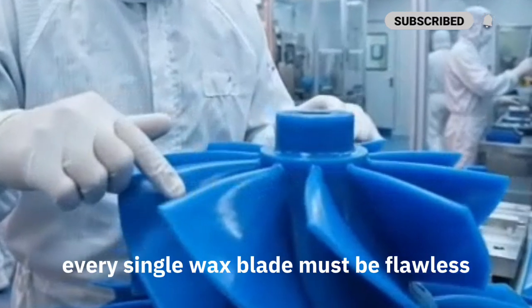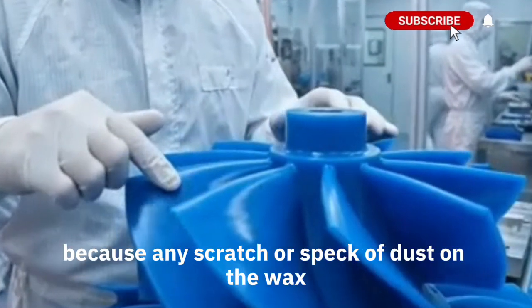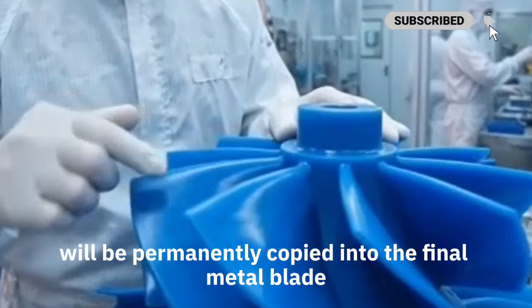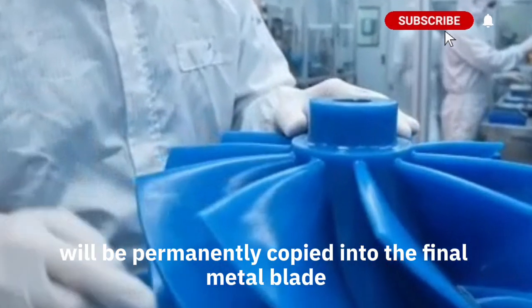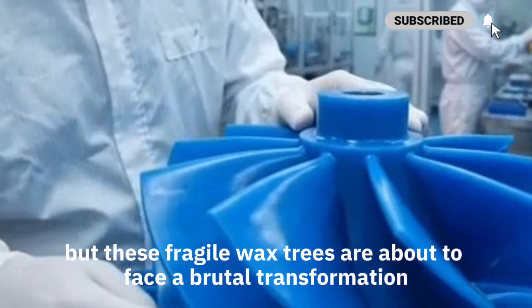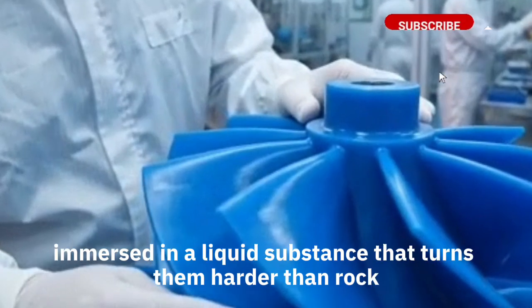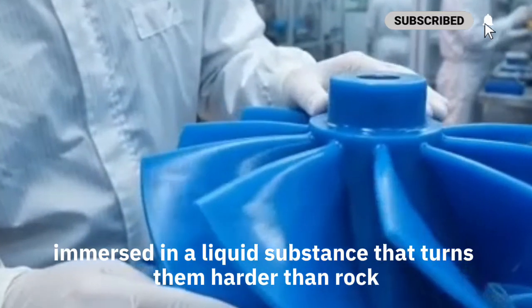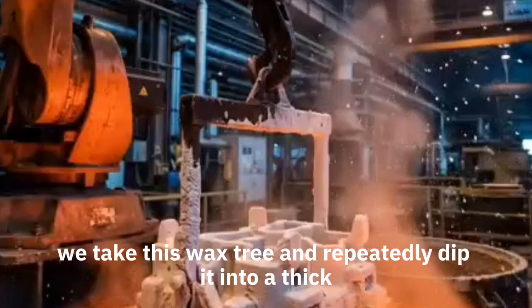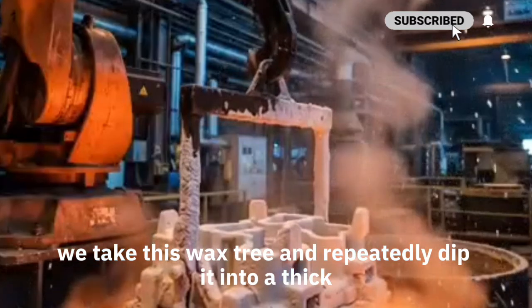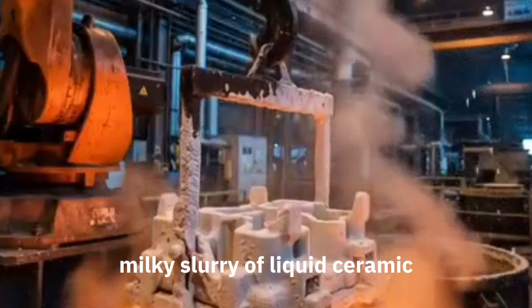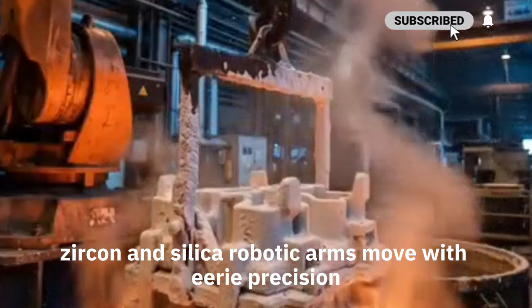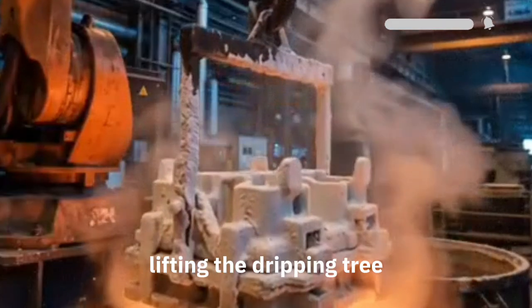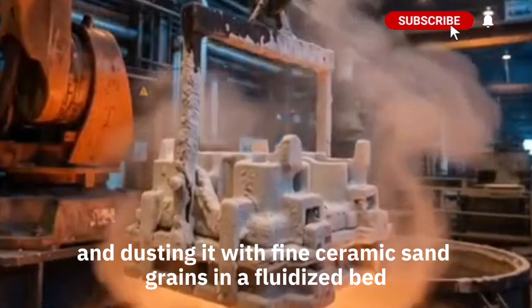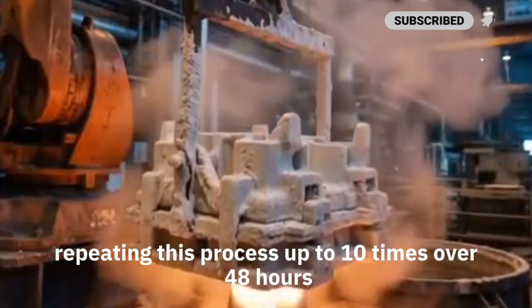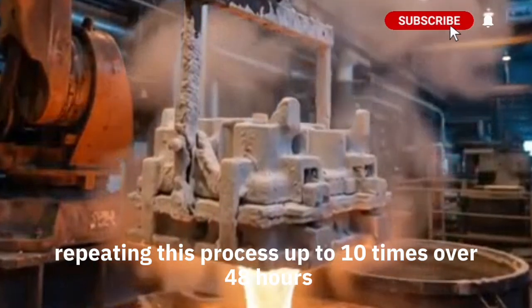Every single wax blade must be flawless, because any scratch or speck of dust on the wax will be permanently copied into the final metal blade. But these fragile wax trees are about to face a brutal transformation, immersed in a liquid substance that turns them harder than rock. We take this wax tree and repeatedly dip it into a thick, milky slurry of liquid ceramic zircon and silica. Robotic arms move with eerie precision, lifting the dripping tree and dusting it with fine ceramic sand grains in a fluidized bed, repeating this process up to 10 times over 48 hours.